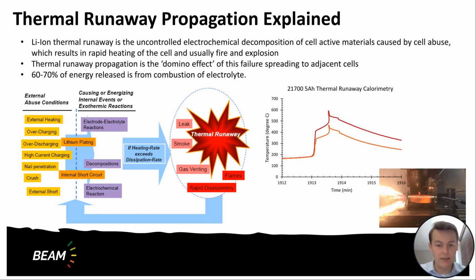obviously excessive heating. And so you can see on the curve on the right here is basically very slow overheating of the cell in an accelerating rate calorimeter, which we use to examine those thermal runaway threshold temperatures. And you'll see that the cell heats up to a point where that separator melts, and you just get a very rapid, over a couple seconds, sort of energy dumping throughout that cell. And as you see in the picture here, it's quite a violent reaction where the electrolyte will be pressurized, it will release through a safety vent in the cell and combust upon exposure to air.